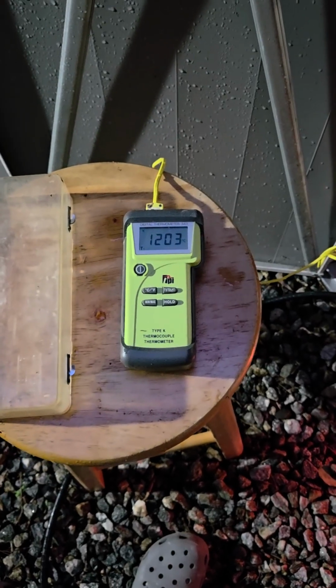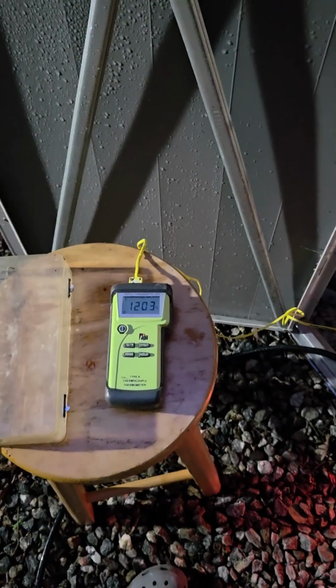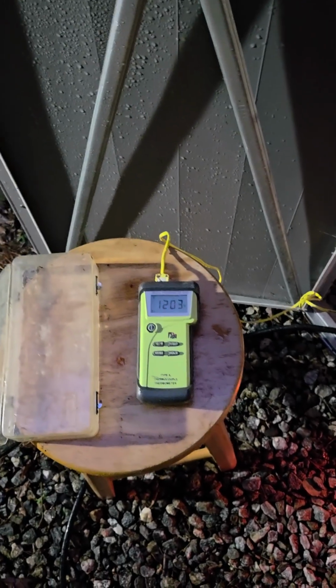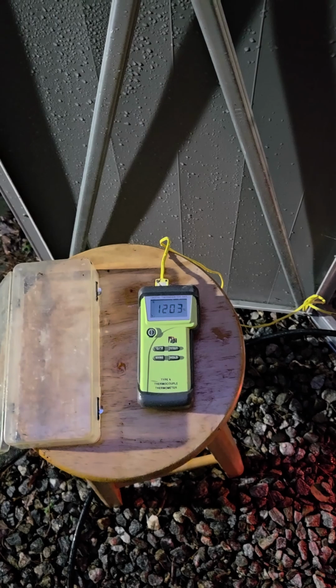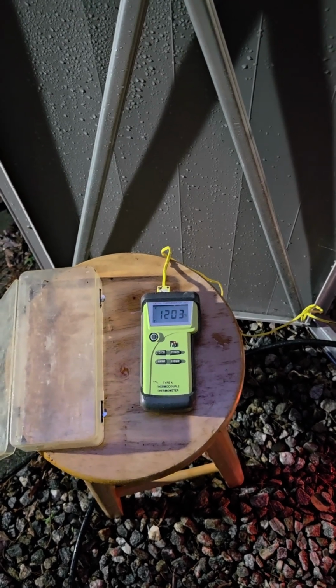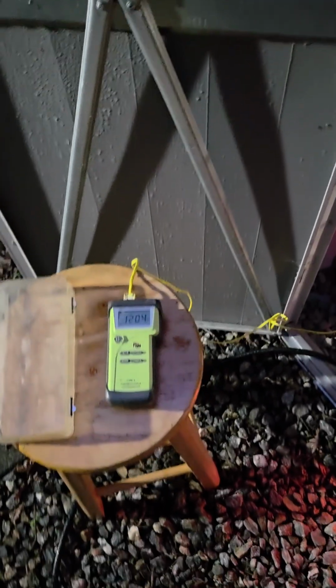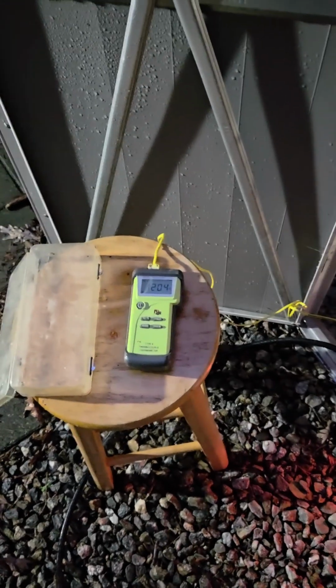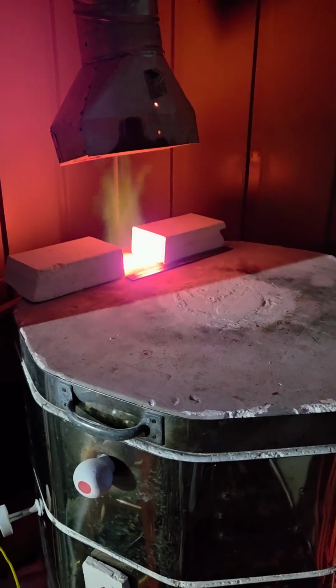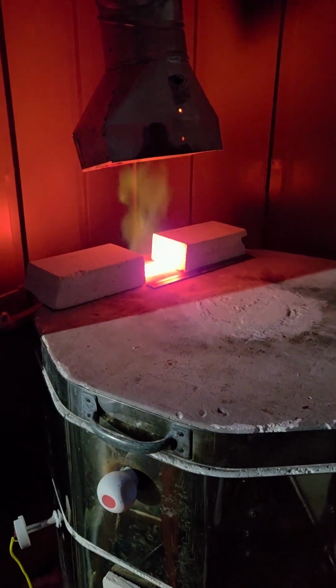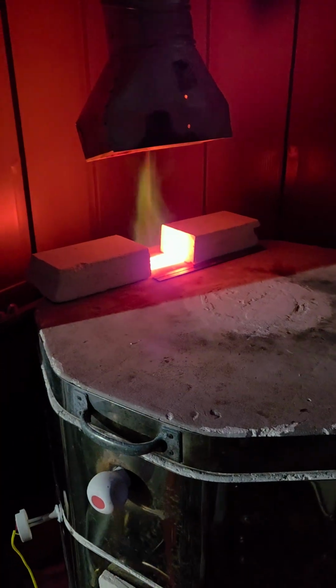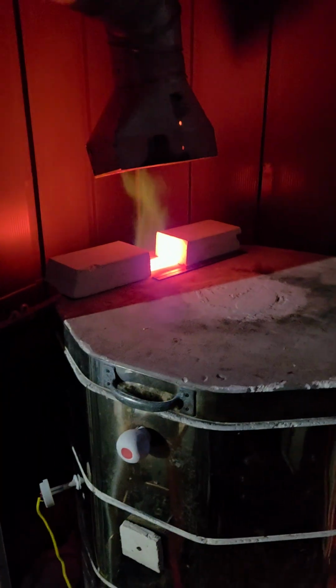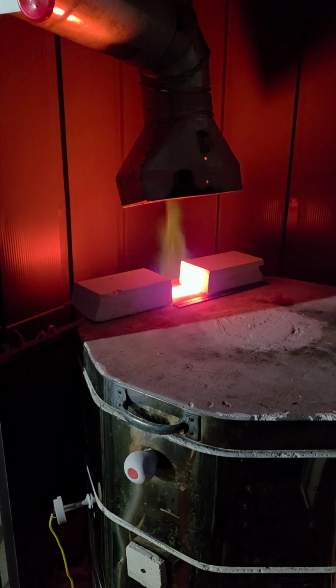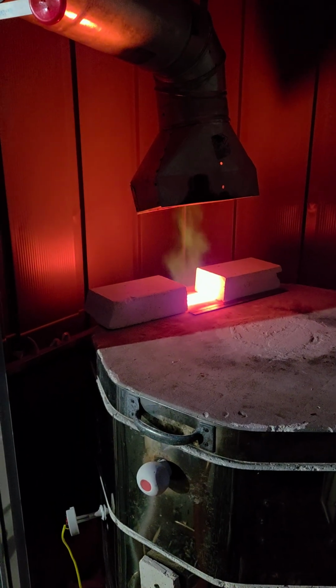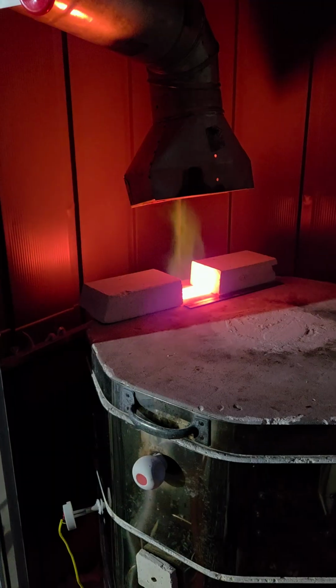At 1197, I did another timing run for about 5 minutes, which showed a temperature rise of approximately 80 degrees per hour. And we're within the last 100 degrees, so per the cone charts, we want to have an average rise of approximately 60 degrees per hour, so that's what I'm shooting for.